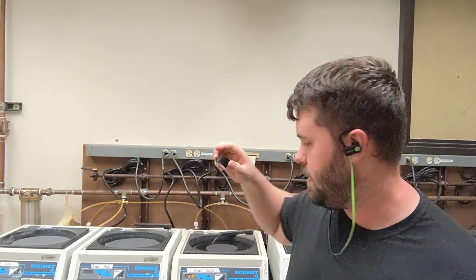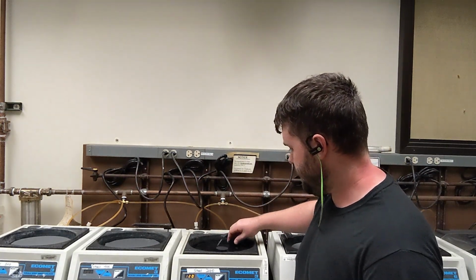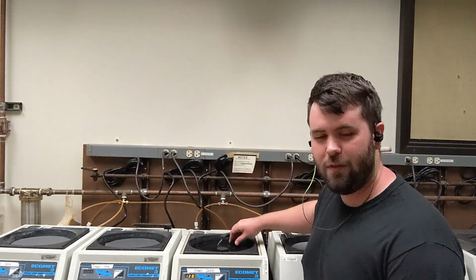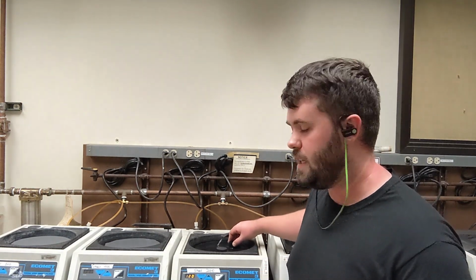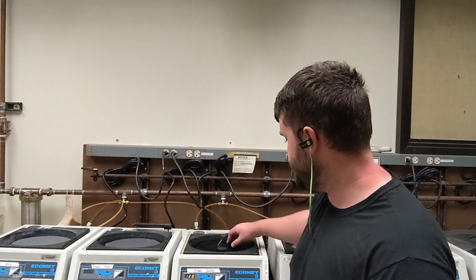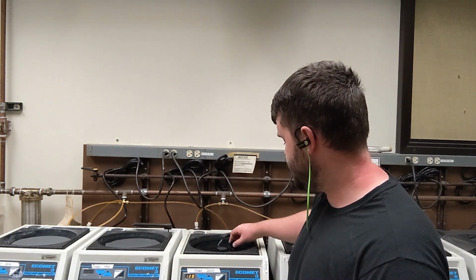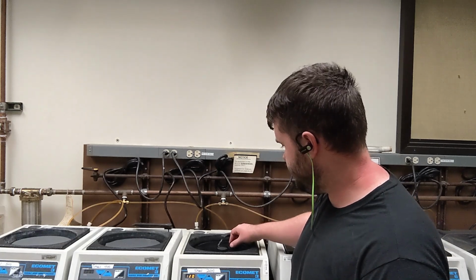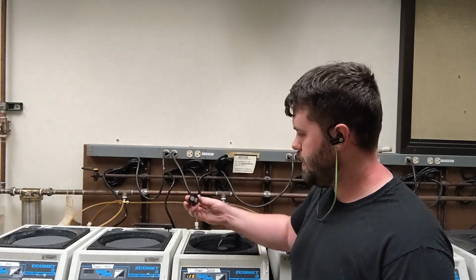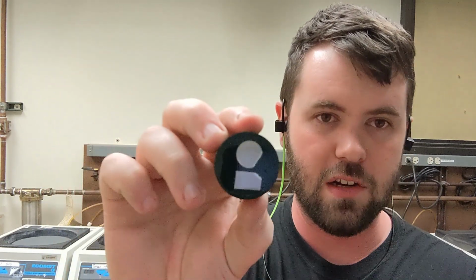To polish, it's not that hard. It does take some getting used to the technique. Basically, you want to make sure that you are pressing down firmly and evenly, like so. And then about every 15 seconds, you rotate the sample 90 degrees. That is just to ensure that you get an even plane when you polish. After just a few seconds, we went from that kind of gross surface that I showed you initially to this, so we can very clearly see our circle and our rectangular cross section. So we're making progress, but this is going to take a while.